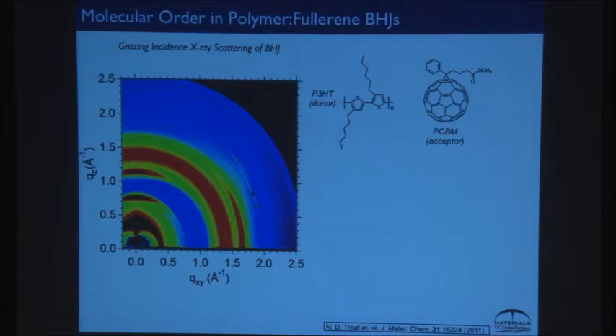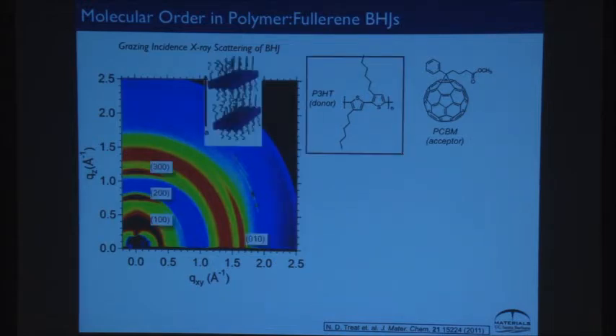Now, if I look at this bulk heterojunction, I'm doing this interesting thing where I have a biphasic material, a blend of this material and this material. And so I take the same kind of diffraction pattern of this, I see some peaks that look like what I saw on the previous slide. And I can assign them, right? So I see the poly-3-hexylthiophene peaks there. But then I see this broad band here, okay? And that's the fullerene.